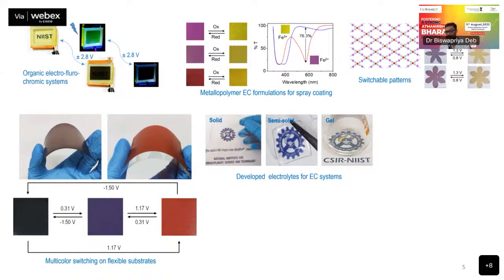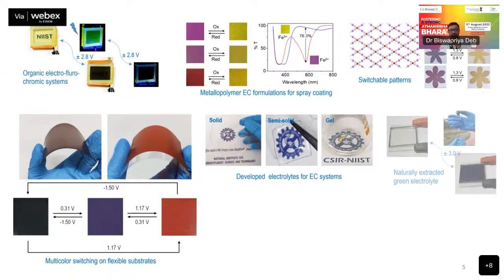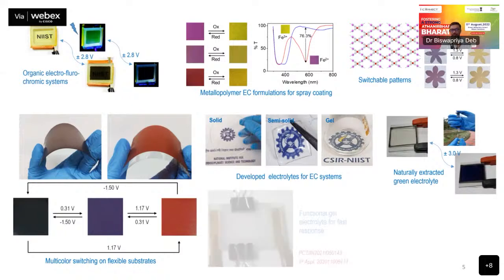We developed our own electrolytes that can go in these devices, and these are very, very stable. If we make a device, it can last for years, as we tested, with no degradation. Both solid, semi-solid, and gel electrolytes are available. Since electrolyte preparation is a problem, we are also now using natural extracts for green electrolytes, which is showing superior electrochromic performance, and which we'll bring out later.